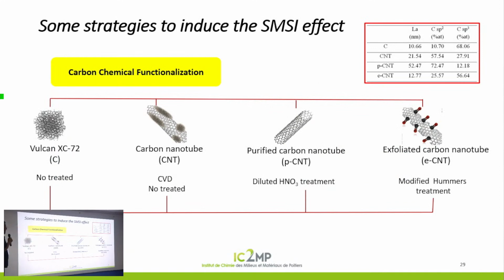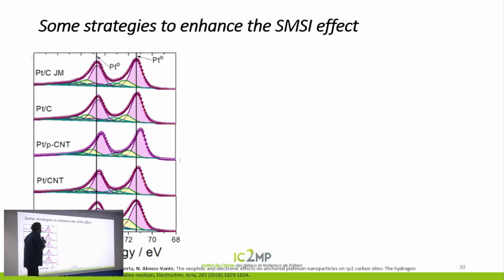And therefore, we studied this from solid Vulcan carbon and carbon nanotubes treated differently chemically in order to change the amount of sp2 at the surface of this material. With the help of Raman, we can determine the crystallinity length corresponding to sp2 and see if there is a difference in their catalytic activity. Okay, I will make the story very short.